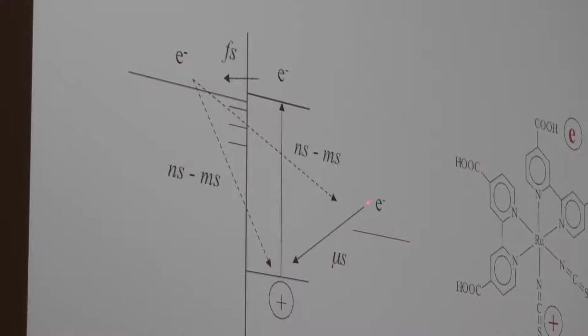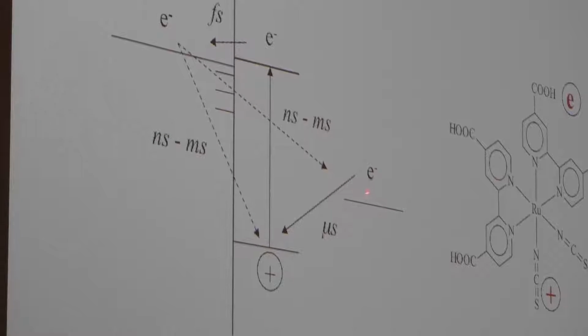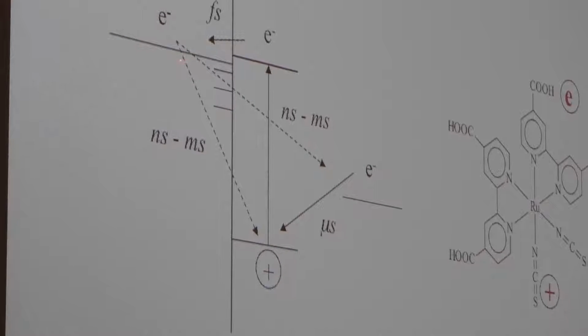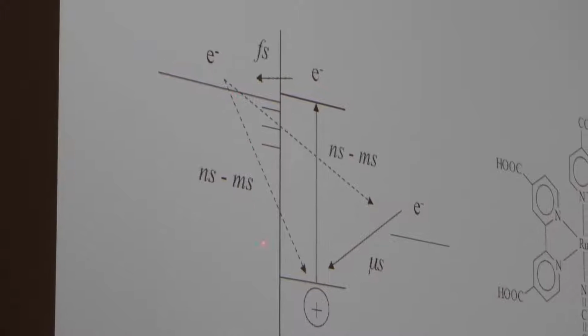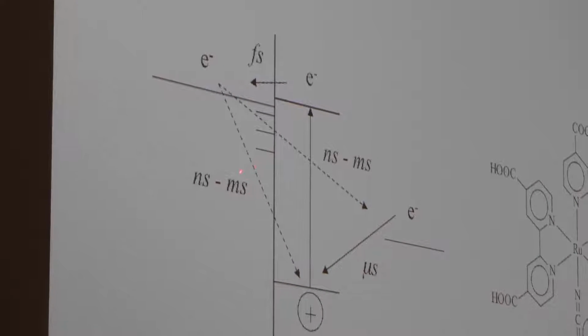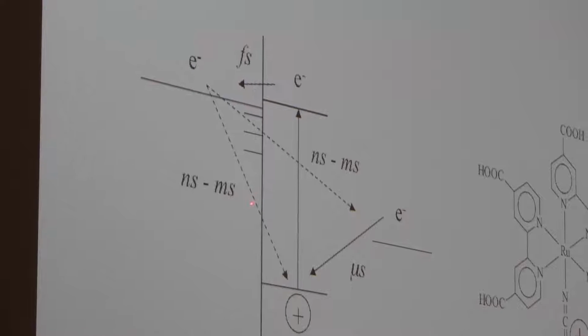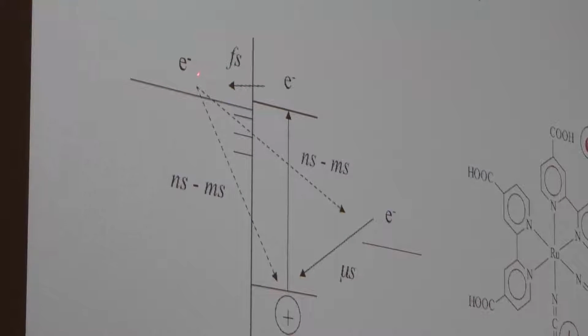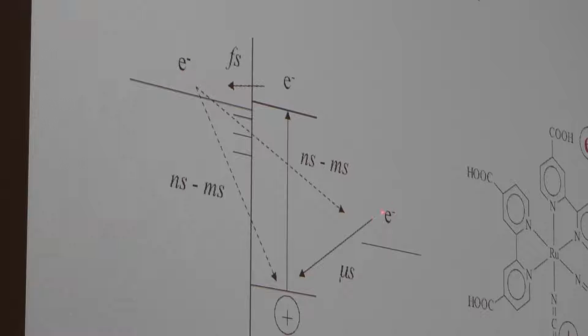Regeneration is the key for further improvement, I would say. Typically microseconds, and then we have the loss reactions. The electron can react back to the oxidized dye. This depends a lot on light intensity, but is typically milliseconds. Or, which is often the case, the electron is lost to the electrolyte, and that's also a millisecond time scale, let's say. And these two processes are what we have been working on in the last years to improve efficiency: looking into the regeneration process, and also how we can avoid this loss reaction from electrons to the electrolyte.